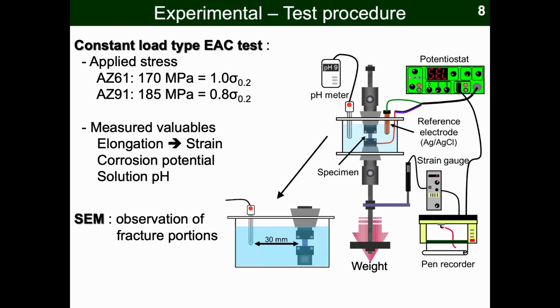I conducted the EAC test using a constant load type test with a reaction vessel. The reaction vessel has a reference electrode, pH meter, and solutions. And a dead weight corresponding to the proof stress was applied to start the EAC test. And during the EAC test, elongation, corrosion potential and solution pH were monitored simultaneously.